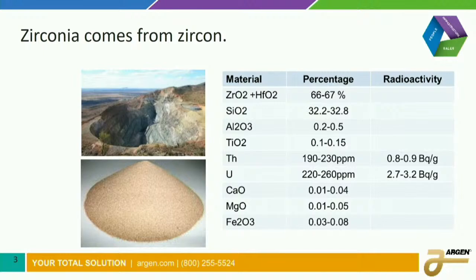Now, I was asked a question last night, does any metal leach out of the zirconia material? And the answer is no. And the reason for that is when you combine, the ZR means zirconium, that's the metal, and then of course O2 means oxygen. There are 2 oxygen atoms for every zirconium atom. When you combine oxygen with the metal, it changes the nature of the material. And in the case of zirconia, it makes a very inert material. So the zirconium is never going to come out of the zirconia.